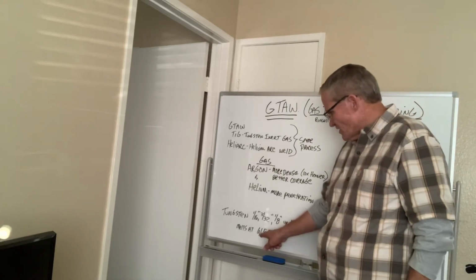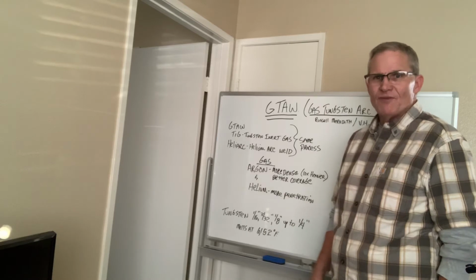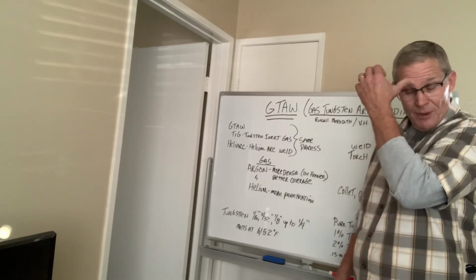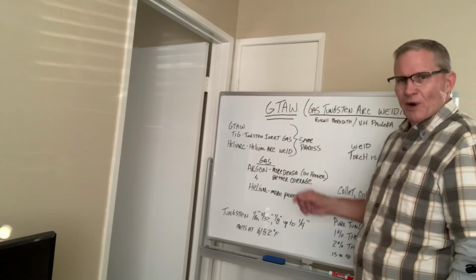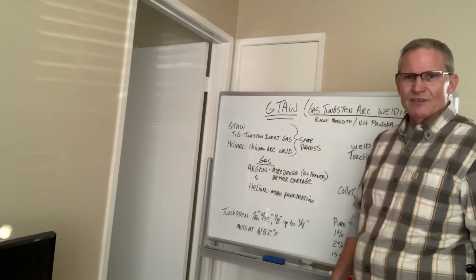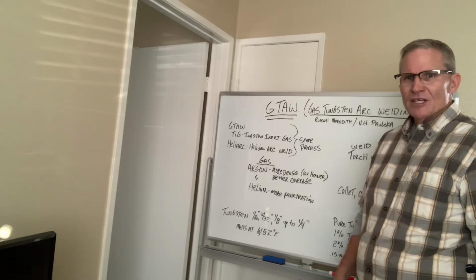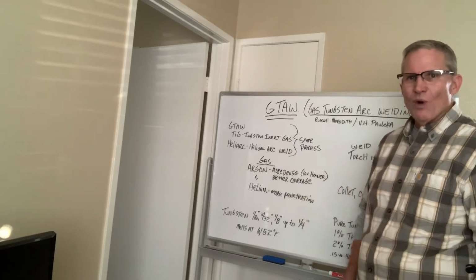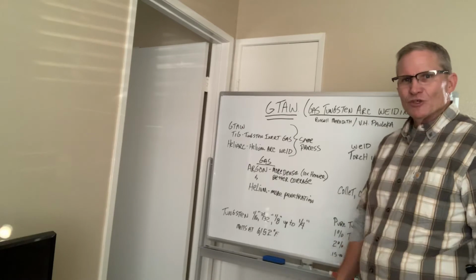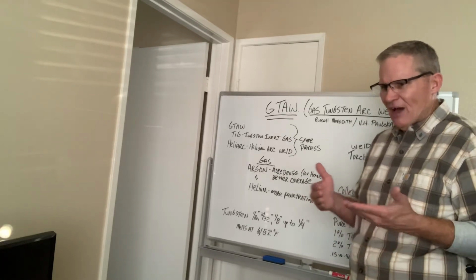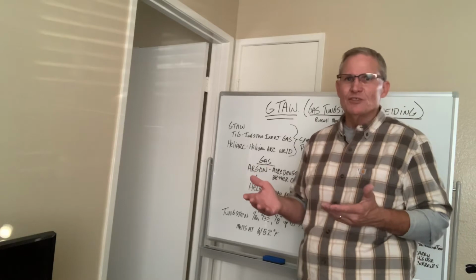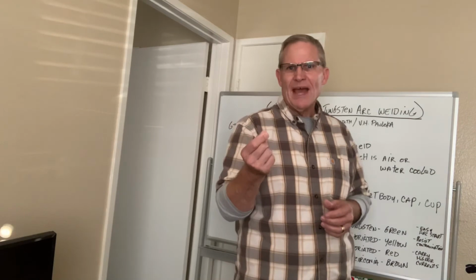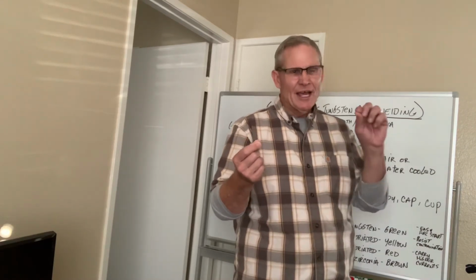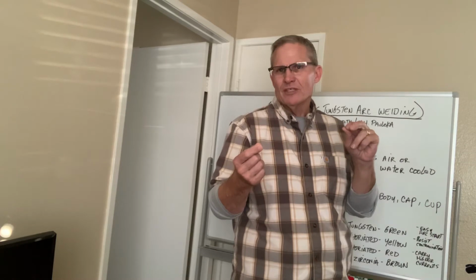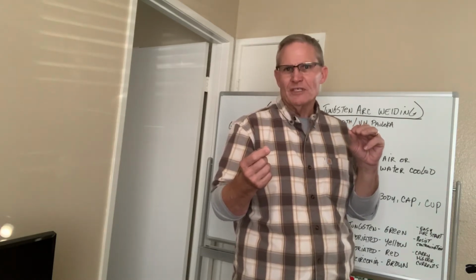The tungsten melts at 6,152 degrees Fahrenheit. The interesting thing about that is that this welding process is somewhere between 11 and 14,000 degrees Fahrenheit. So you might be asking, how is that possible? Why is it that the tungsten doesn't melt as you're doing the weld? And it's because of the heat transfer, how quickly the heat transfers. An easy way to explain it is that an ordinary match is 3,000 degrees Fahrenheit, and a piece of aluminum melts at 1,220 degrees Fahrenheit.